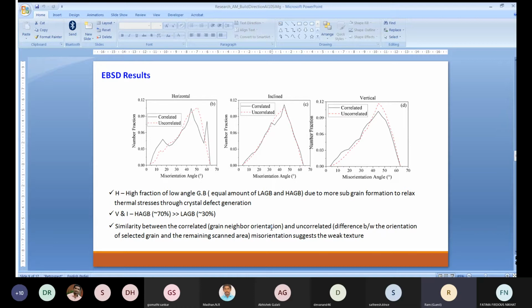Here the misorientation angle of each grain with respect to the number fractions was plotted for all three directions, horizontal, inclined and vertical, in correlated and uncorrelated conditions. Correlated means in a full grain structure, take a particular grain and compare it with its neighbor, and when you go to the next grain, it is compared with its next neighbor, like that. Whereas in uncorrelated, we fix a particular grain and calculate the misorientation angle with respect to all other grains in the micrograph.